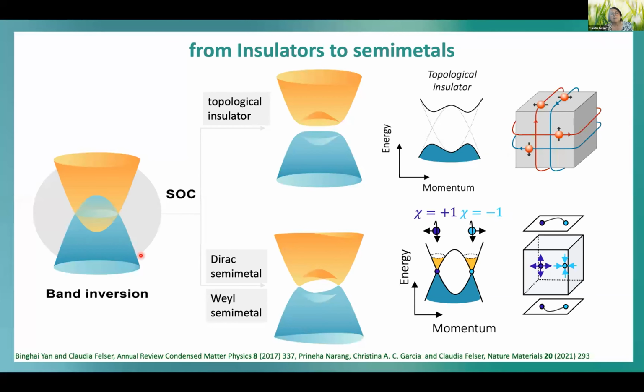But there is very often more symmetry in the crystal, and then we might have bands which stay connected, so they are maybe protected by chirality, by rotation and so on. And so depending where these connected points are, whether they are at high symmetry points, we have Dirac semimetals. When they are at low symmetry points or in magnets, we have Weyl semimetals.